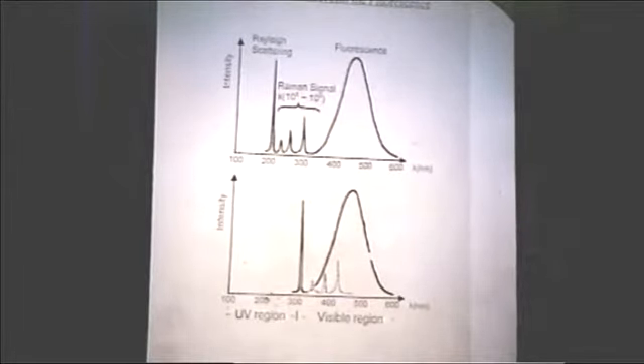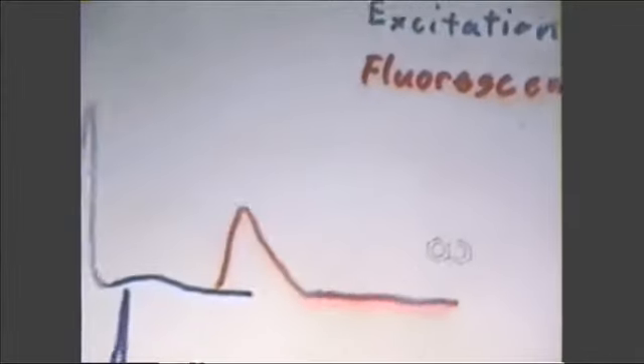The advantage of this is that you don't have this problem of losing intensity due to the fourth power dependence. In fact, you enhance your intensity due to the fourth power dependence. And secondly, if one is interested in looking at a hot sample, you don't have the problem of interference from the luminescence, because all of your detection is done at such short wavelengths, such high energies, that the luminescence is very small in that high energy region. So where do we need to go in order to get below the typical fluorescence that we might expect for coke on a catalyst surface?